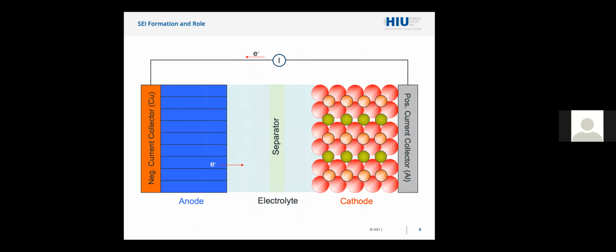What is this SEI? How does it occur, and what is its role? So if we consider we are charging a lithium-ion cell, that means we are forcing electrons into the negative electrode. These electrons obviously reach the interface with the electrolyte. A series of reactions, usually rather irreversible at the beginning, leads to the formation of an SEI, this solid electrolyte interphase, which we will see later. The great advantage of this SEI is that it is blocking the transfer of electrons from the electrode to the electrolyte. So it's blocking the reaction occurring at the interface after some time, but it's still enabling the passage of lithium ions, which then leads to the charge of the lithium-ion cell.